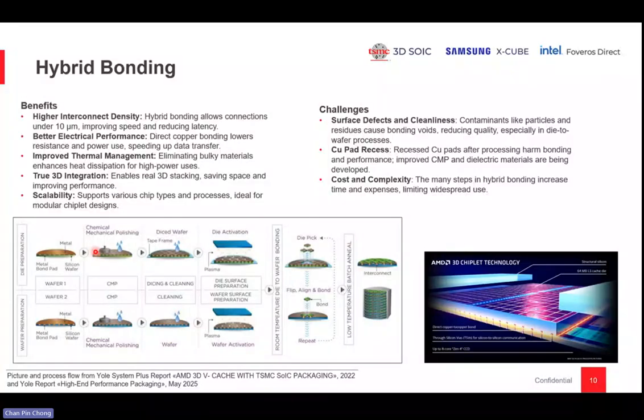So here is basically a process flow extracted from a presentation from a Yole report. Okay, it's basically the example of the HBI flow. Basically, the top shows a die to wafer bonding, and it shows preparing a base of a metal and then a CMP polish, a dice wafer, a dice activation. It could be a plasma activation, and then you have the wafer prep, you have the CMP, you have the clean, and then you have the wafer surface prep, and then here you have the bonding, right? Flip, align, and bond. So you could do this with either wafer to wafer bonding or die to wafer bonding.